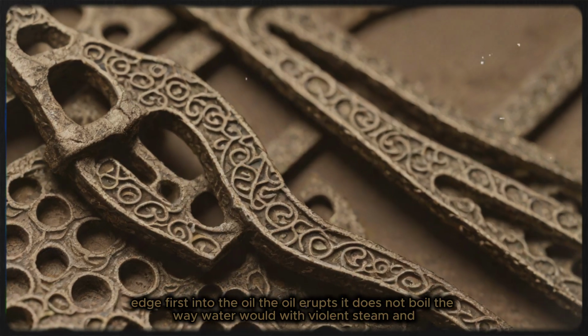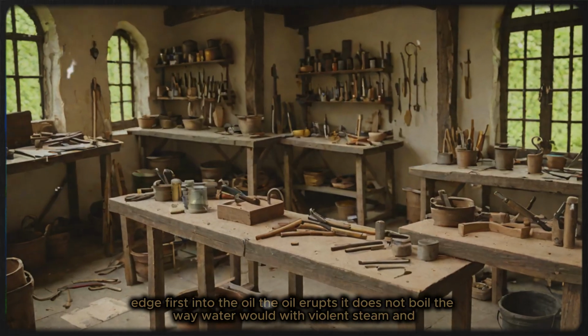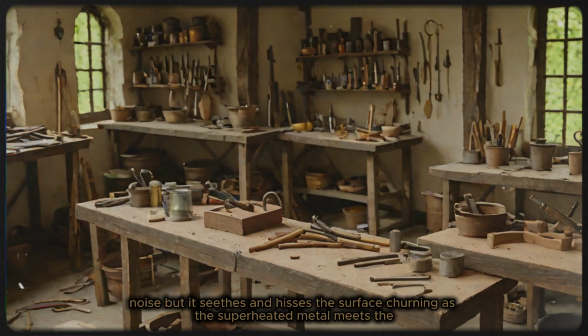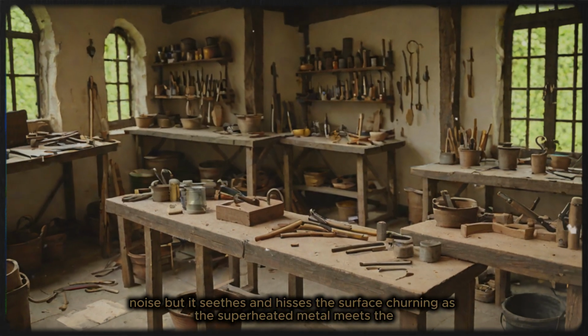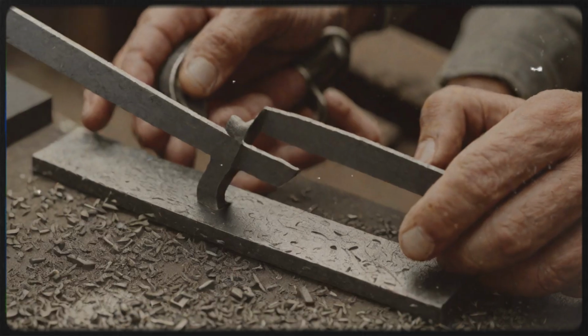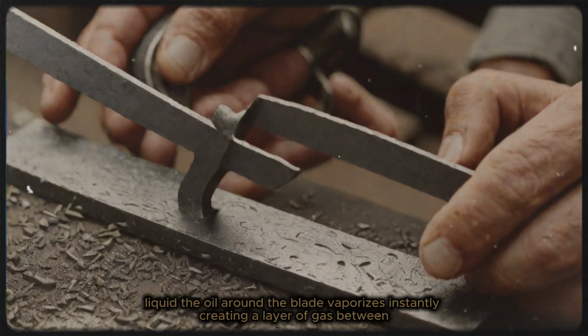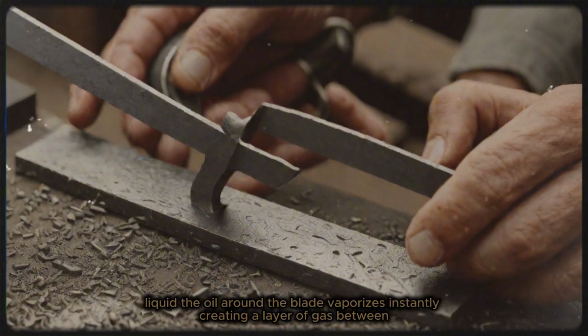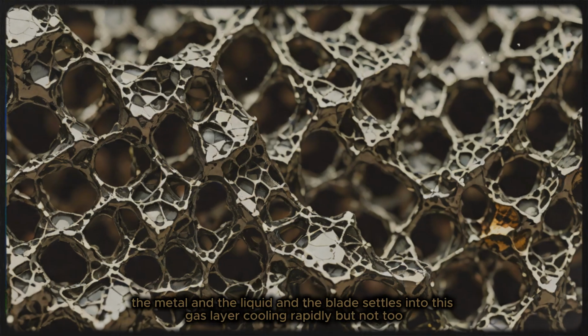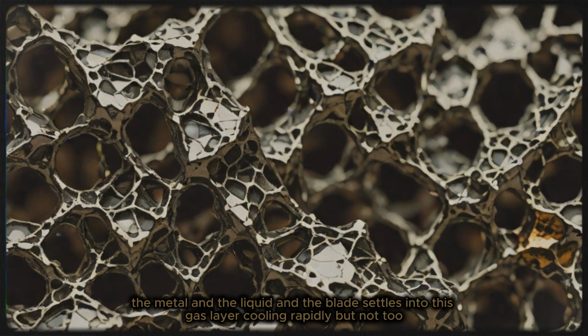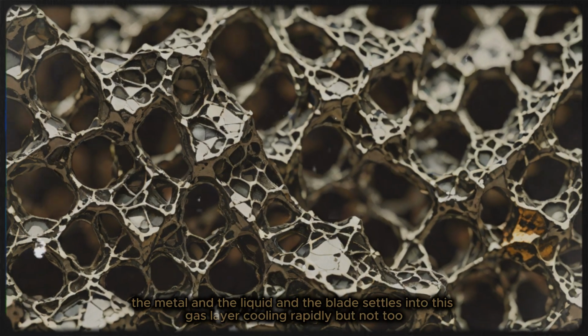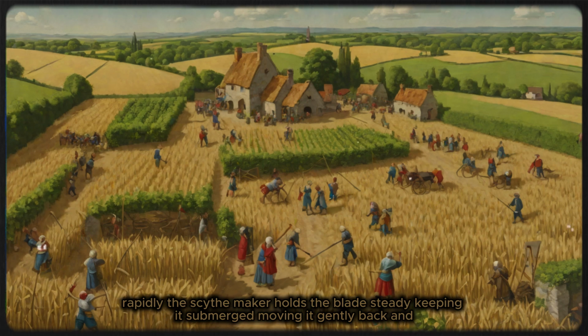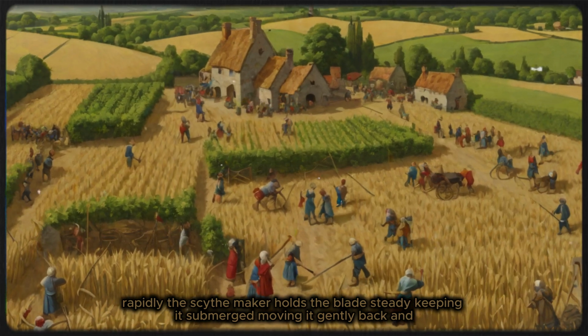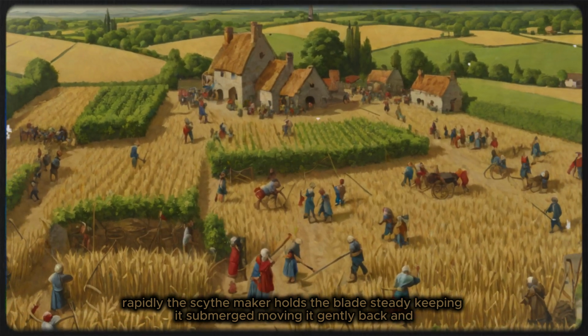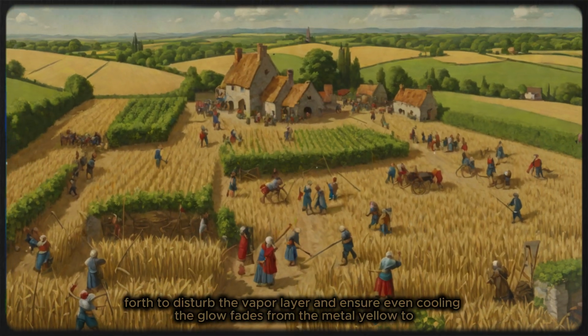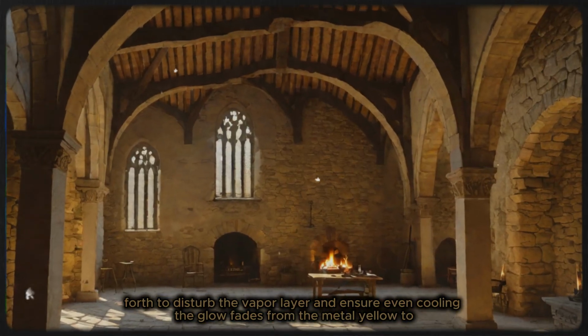The oil erupts. It does not boil the way water would, with violent steam and noise, but it seethes and hisses, the surface churning as the superheated metal meets the cooler liquid. The oil around the blade vaporizes instantly, creating a layer of gas between the metal and the liquid, and the blade settles into this gas layer, cooling rapidly, but not too rapidly. The scythe maker holds the blade steady, keeping it submerged, moving it gently back and forth to disturb the vapor layer and ensure even cooling.